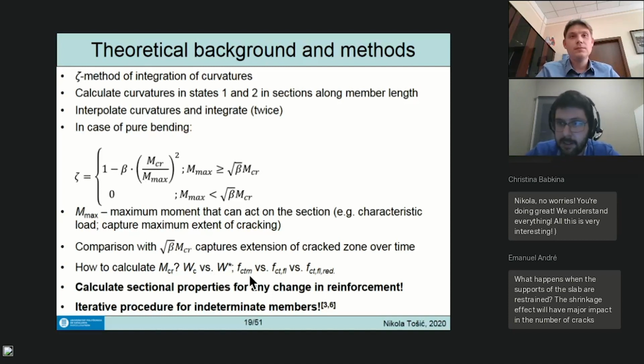So far, that is what has been recommended and mostly used. ACI before had its rupture modulus, which is basically the tensile strength, but they recognized later that you should not use the full rupture modulus because of the effect of shrinkage. So now ACI says reduce the rupture modulus to 2/3. And what does that mean? That's the one-third that you lose due to shrinkage. They don't have beta, so it's a different way that they do it. So you can use FCTM, you can use flexural, or you can use the reduced flexural — take the full flexural, calculate how much is eaten up by shrinkage, and then use that.